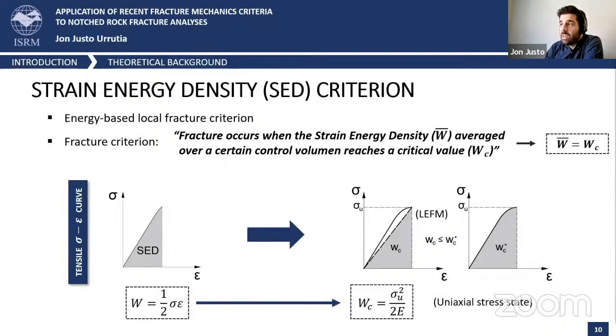Under the area defined by the triangle, which is defined by the tensile strength and the Young modulus in this case. In general, rocks are assumed to present a roughly linear behavior, but in any case, it should be expected to obtain a lower value of the critical strain energy density than that calculated from the real tensile stress-strain curve. So in this case, apart from the tensile strength, we also need the deformational parameters of the rocks. So we have to define both the Young modulus and also the Poisson ratio.